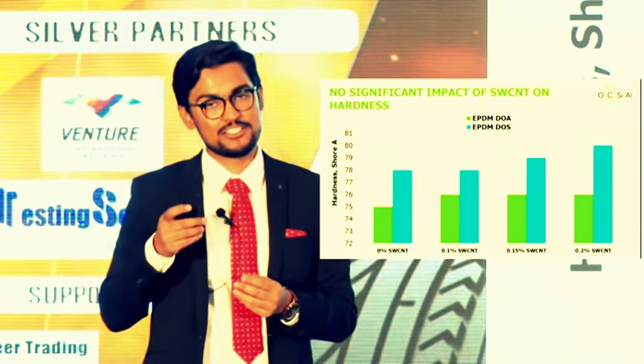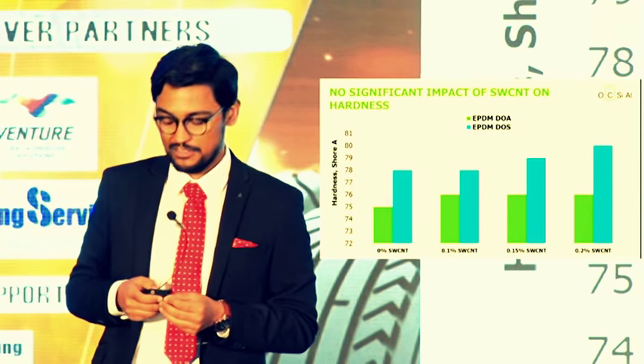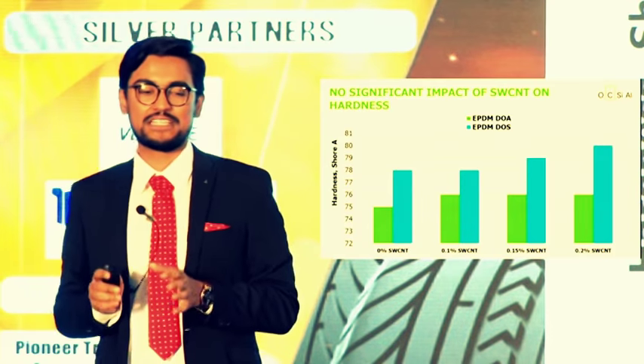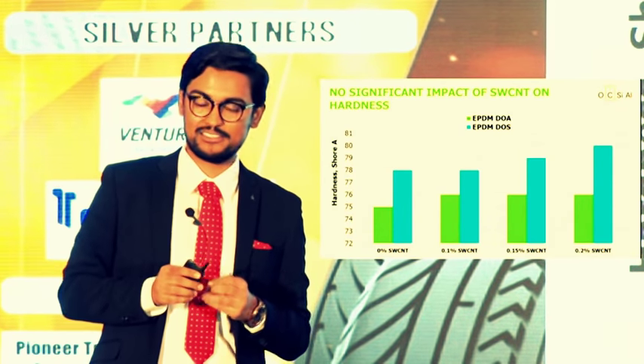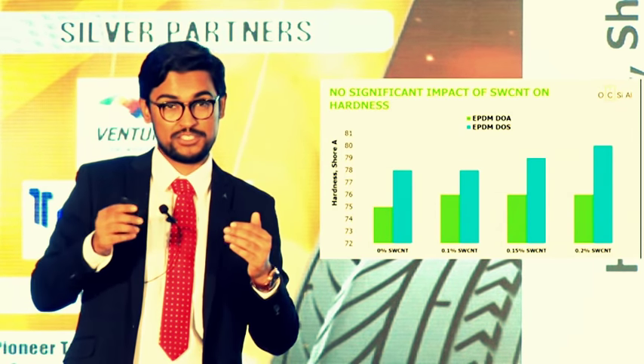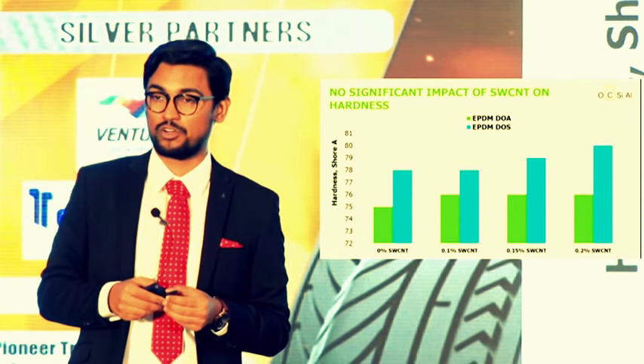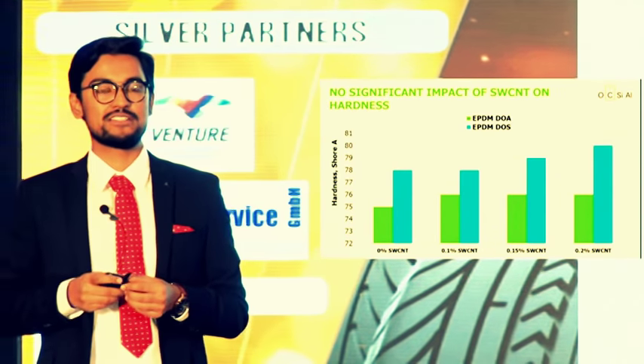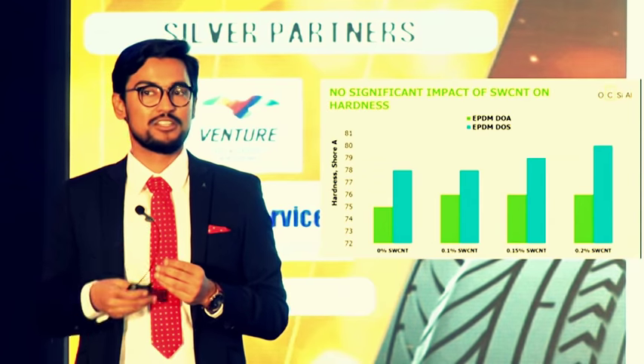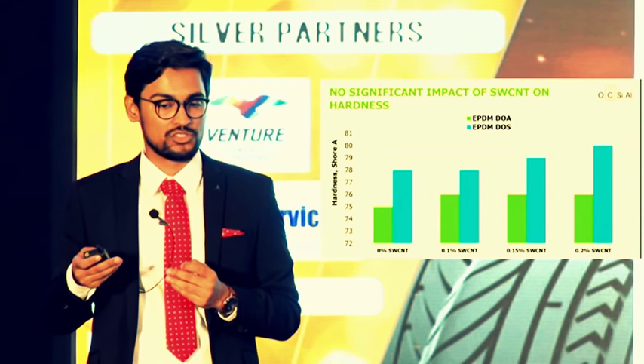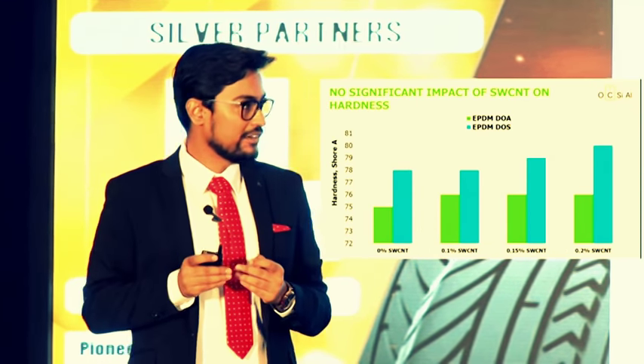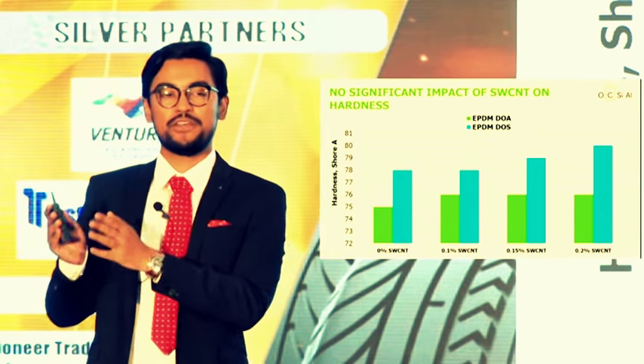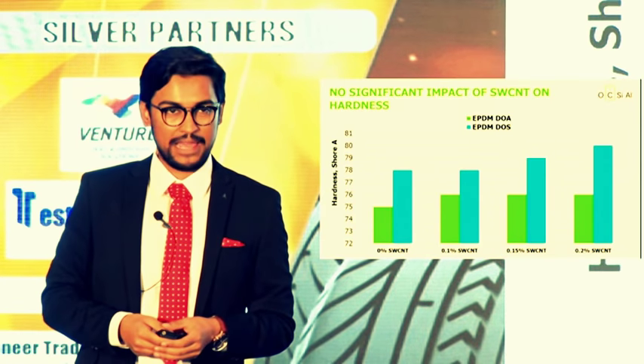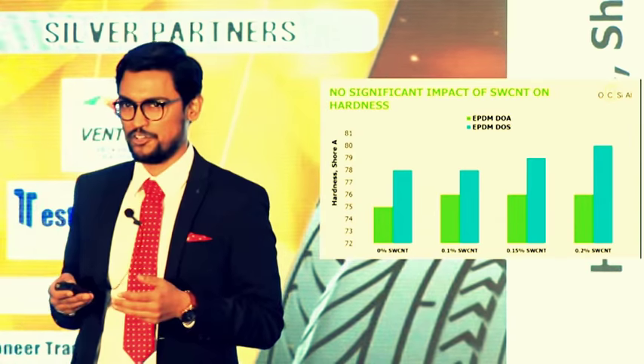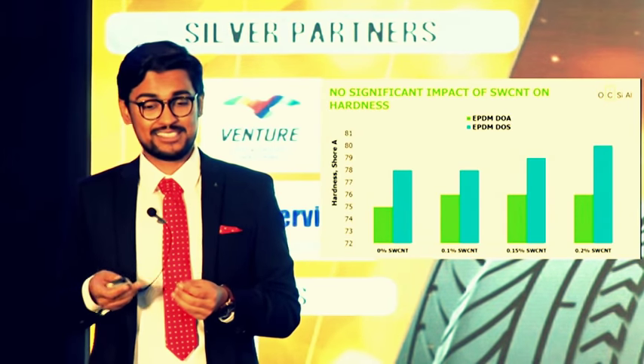Now let me get into depth of it. We saw that there was no significant impact on hardness of the whole compound after addition of single-walled carbon nanotube, which is very important in case of extremely high hardness compounds. This particularly is a pain point when you compare it with other fillers like carbon black and other fillers which have high aspect ratio, because addition of them increases the hardness a lot.